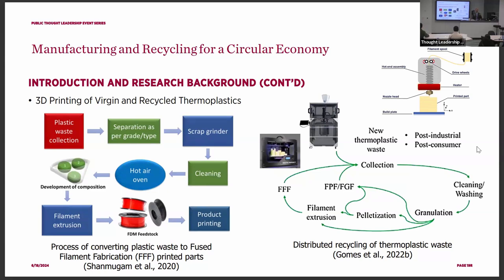You can see we do the separation, then the scrap grinding, cleaning and drying. Then we develop the composition and do the filament extrusion. After that, we put it into the 3D printer to do the printing. That's the FDM, or FFF, process. In such a process, the particle waste will experience at least one or two more heat cycles. That is a bit wasteful, because research found that six heat cycles would be the limit for such particle waste material. Otherwise, the degradation of the material will be severe, so we have to consider this.